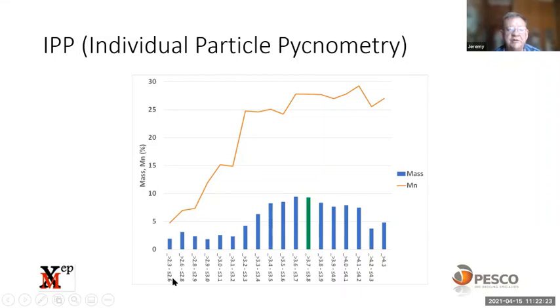You can see they're 2.3 to 2.6, 2.6 to 2.8, all the way up to 4.3. Those lines represent the mass distribution. In other words, how much of the mass of the sample reported to each of those density bins. And then that line represents the manganese content. So you can see that the sample didn't have a great manganese content. We couldn't get anything more than 30.